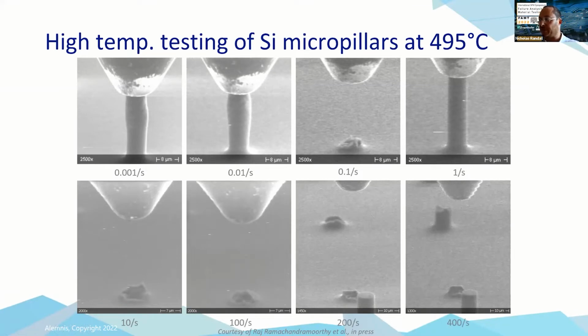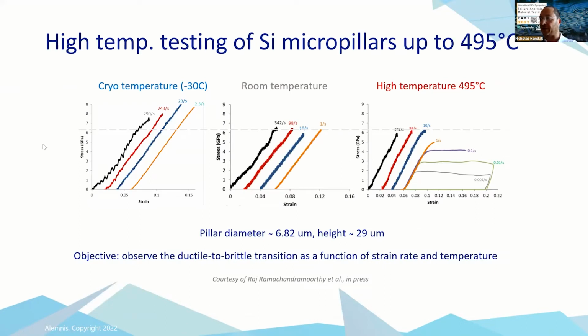0.1, this is the ductile to brittle transition speed. We see that very clearly. And then as we go faster, we've got 1 per second, we've got 10 per second. Now we're very brittle. We're just seeing the before and after because we're moving very, very fast. So you can see that silicon has very different properties depending on the speed of deformation. And of course, that's very linked to the temperature of operation as well. And here you can just see a summary of that. So on these silicon pillars, we did testing from cryo temperatures, so very low, -30, up to 500. And you see this ductile to brittle transition very nicely on the stress strain curve.